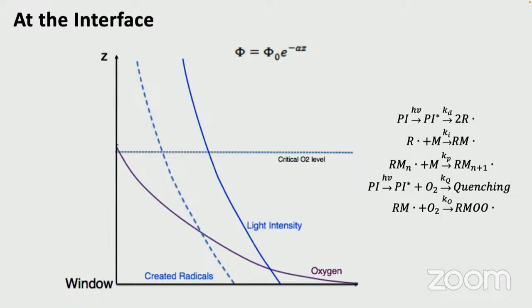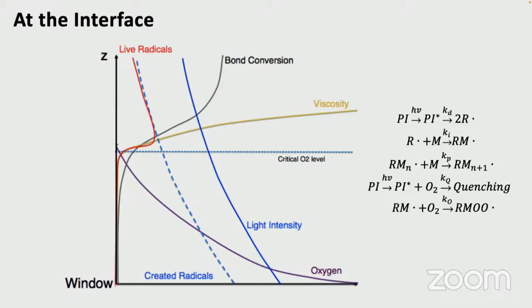As that oxygen concentration gets depleted because the radicals react with oxygen, the oxygen is being replenished through the window, because the window is very permeable, and underneath the window is a source of oxygen. So the oxygen concentration is dropping with distance, and once it drops below a certain threshold, the polymerization will take off. And this distance is the dead zone. That's where the rate of polymerization will take off. There's a gel effect, even a Trommsdorff effect, back to Smith-Ewart kinetics. And this distance is what we monitor.